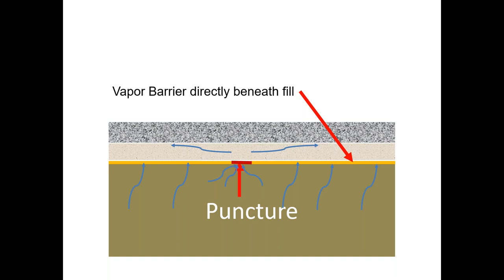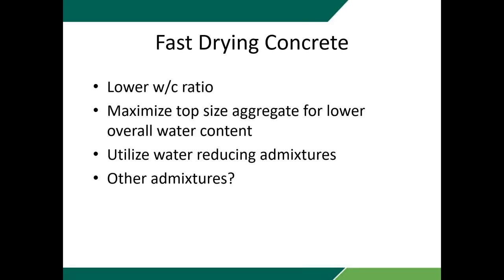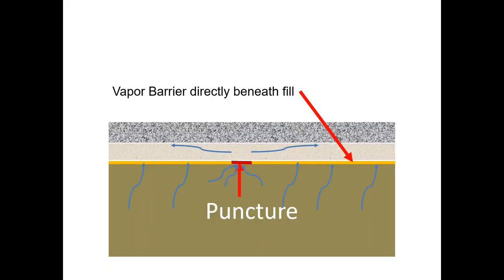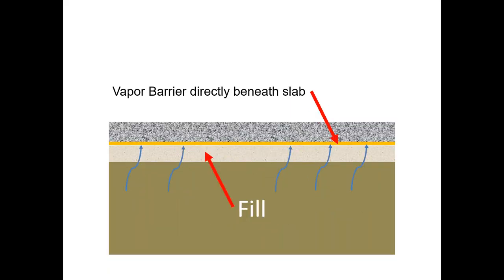So the thought is that by having a saturated sand layer underneath here, it takes that much longer for the slab to dry out, because you've now got basically 100% relative humidity again at the base of the slab. By placing the vapor barrier directly beneath the slab, the water can only go up. It can't go into the sand. It can't saturate the sand. And it does end up moving up and out of the slab quicker than if you had the sand there.